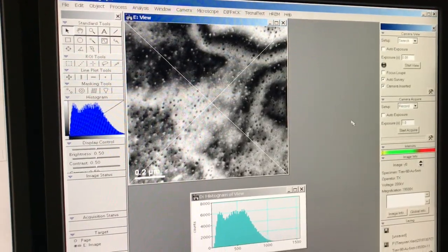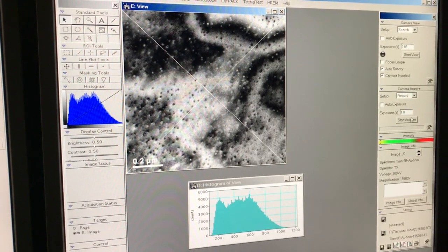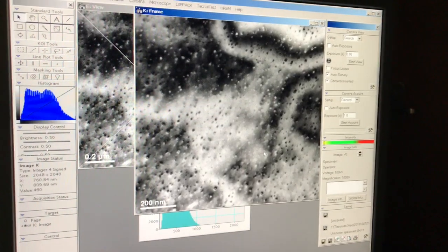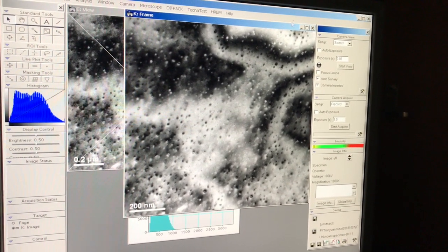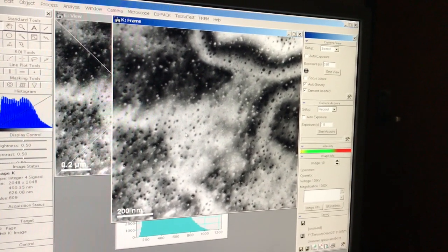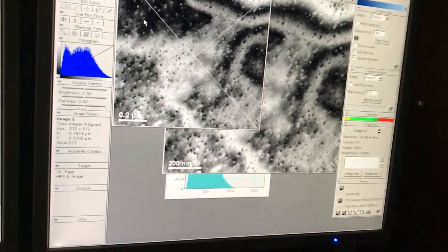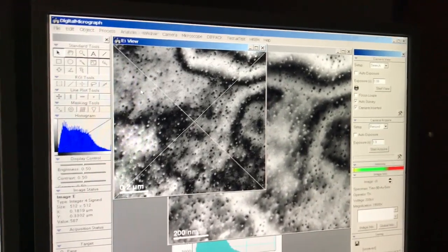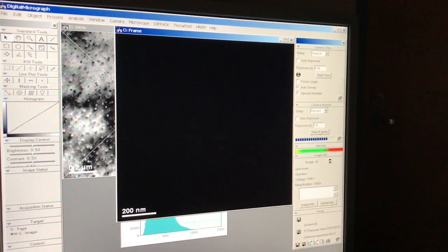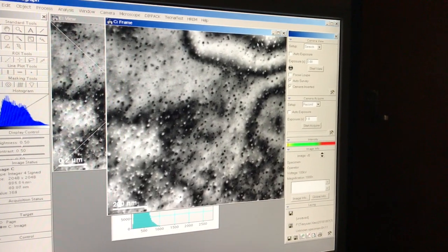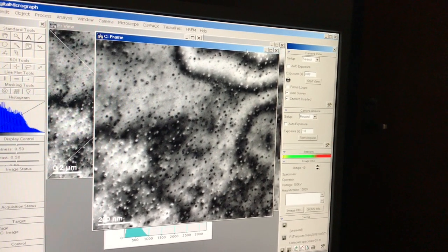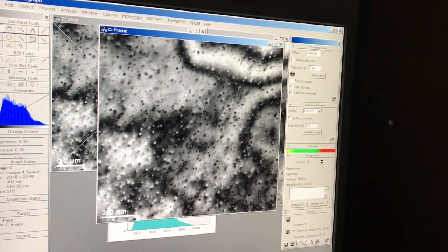And just really quickly here, if we want to do an acquire just to see how these look, I'm going to use a second here. So that's the bright field image, again with S equals 0. So you can see these faulted dislocation loops. Now I have the CDF image. And that's the CDF image. And so now we're going to talk about how to change our imaging conditions to get some sharper